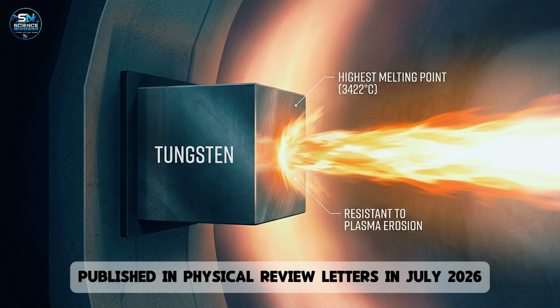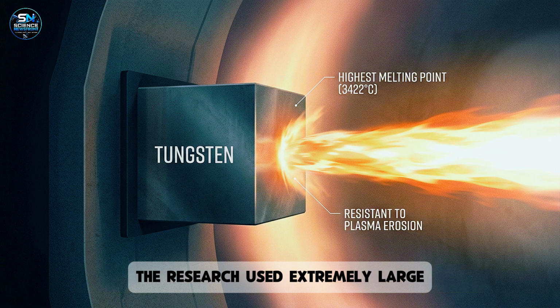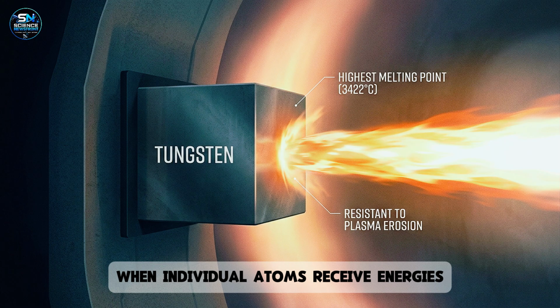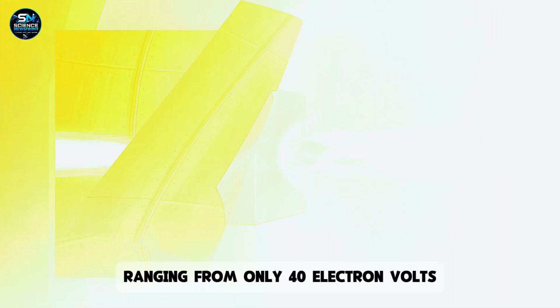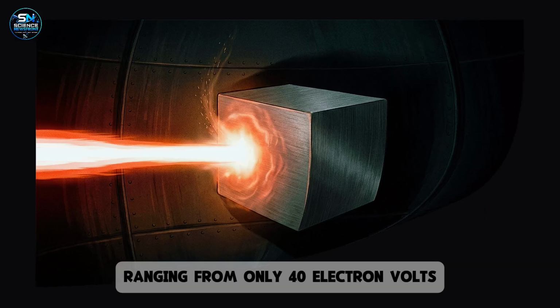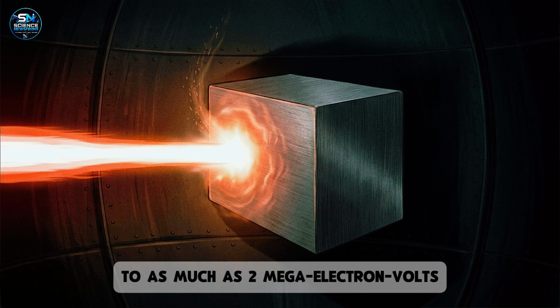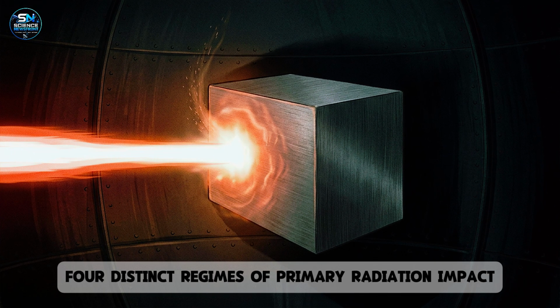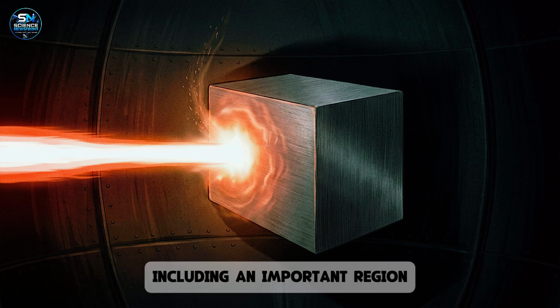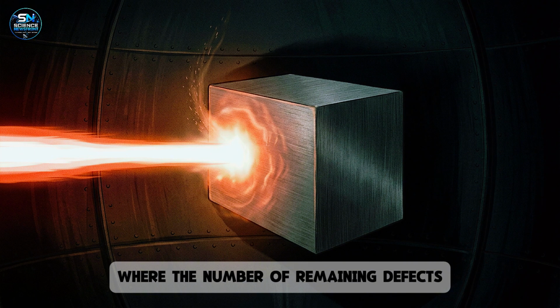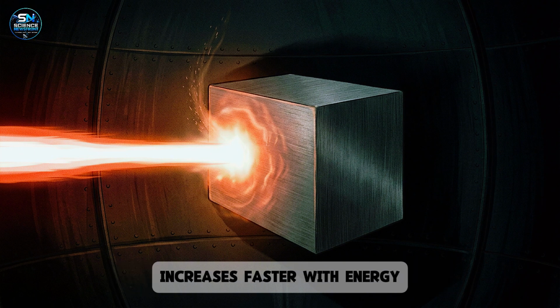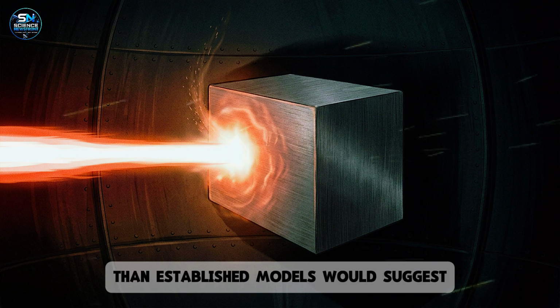Published in Physical Review Letters in July 2026, the research used extremely large molecular dynamics simulations to investigate how tungsten responds when individual atoms receive energies ranging from only 40 electron volts to as much as 2 megaelectron volts. The researchers identified 4 distinct regimes of primary radiation impact, including an important region where the number of remaining defects increases faster with energy than established models would suggest.